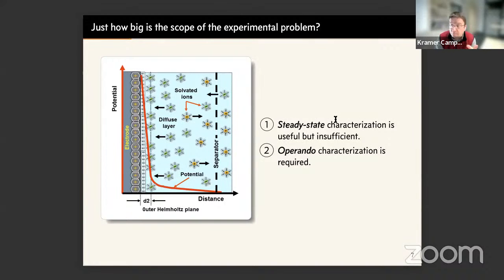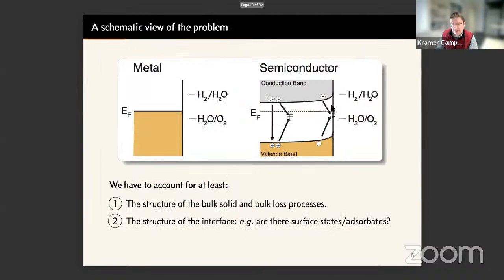So the first, well, maybe problem 0, which I didn't put on this slide, is that there are now several decades of work which make very clear that if we want to characterize this process experimentally, if we want to understand the structure of the bulk, the structure of the interface, and the structure of the liquid, and how these things come together to catalyze electron transfer, you need to do operando characterization of the interface, right? So whatever the surface states are here in this problem, they may be only stable under operando conditions. And if you pull them out of your electrochemical cell and, for example, take them to a UHV chamber, the world could look very different.